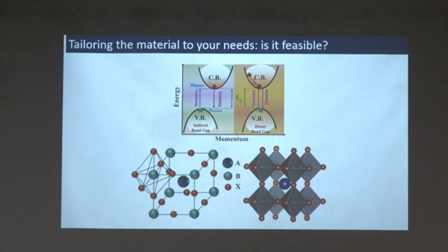And here it is also important because you know from physics that some materials possess so-called indirect and direct gaps. For photovoltaics, direct gap materials are more convenient, more useful and more efficient for application in solar cells. It is one advantage.